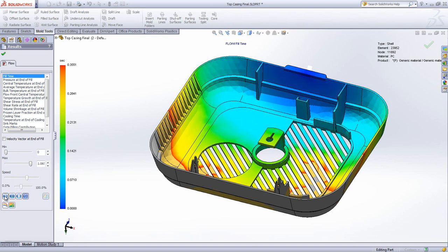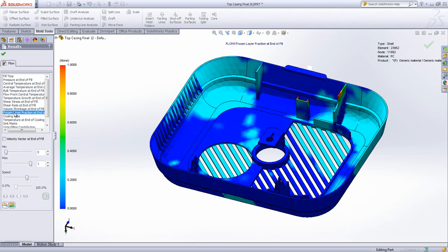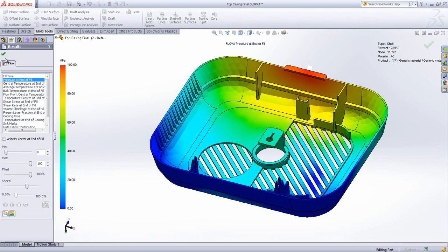Because we decreased the thickness too much, we created a short shot problem. No matter what you do, how you set up the machine, or how fast you inject the plastic, you just can't get the plastic to fill up 100% of the mold cavity. This molded part would be nothing but defects.